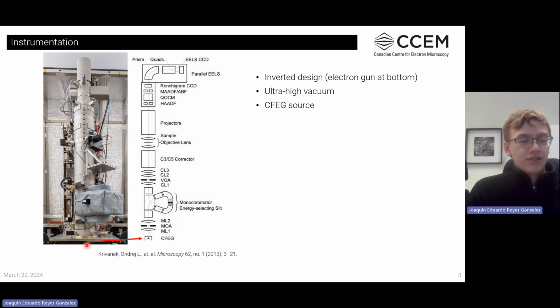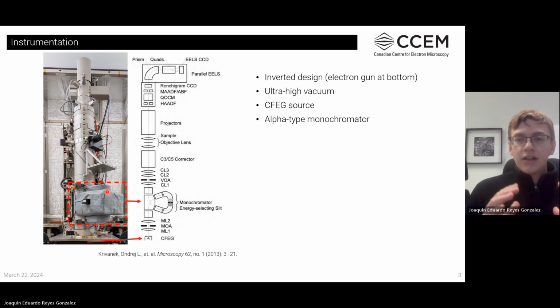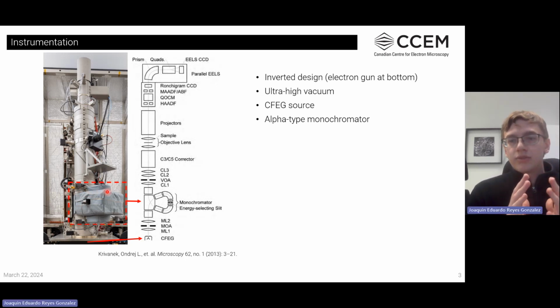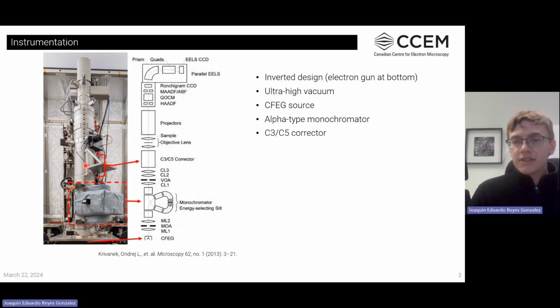This allows us to do some very fine analysis just as is. But to improve how good that beam really is, we take it and we pass it up through this monochromator. This monochromator takes the beam, narrows down that energy spread and takes out some of those chromatic aberrations. Then it puts it through our condenser system, passes it through a C3, C5 corrector, which corrects for some of those geometric aberrations that are present in the probe.